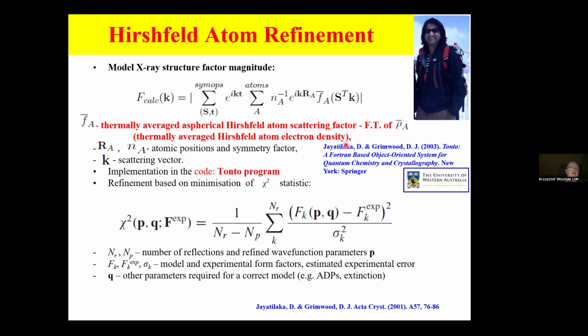Then we can simply collect X-ray diffraction data. This doesn't have to be high resolution. And we play with the model and minimize the differences between moduli of structure factors from our model and those from experiments. We can measure these differences by using a chi-square test.